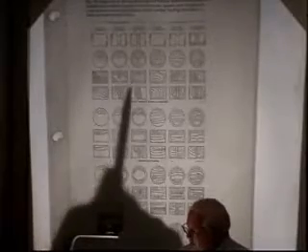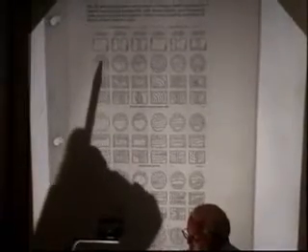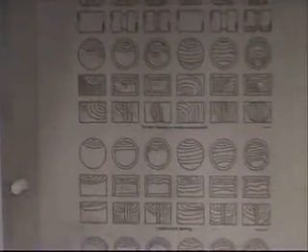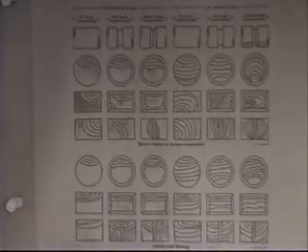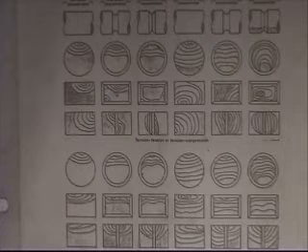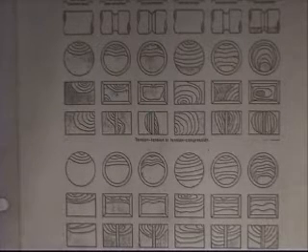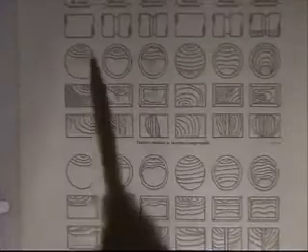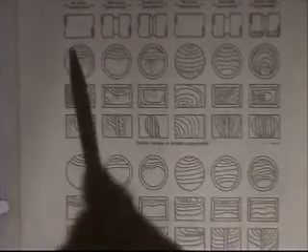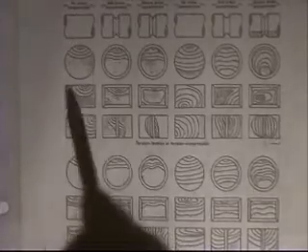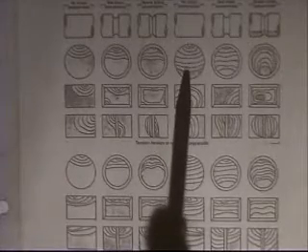If the final fracture area is large, so this is supposed to be, these little lines here are called the beach marks. As the crack grows, it will leave behind marks, just like a tide going out will leave trash up on the beach. Okay, it'll leave these little marks behind, or the tide going out will sometimes leave ripples in the sand. Most of the time it's smooth, but it'll leave these beach marks. And so that's the region where the fatigue is. There's a different texture there than the final overload. If it's a high average stress, the part has a high stress on it, you'll see a large area. If it's a low nominal stress, you'll see a small area, and the fatigue crack will cover most of the area.